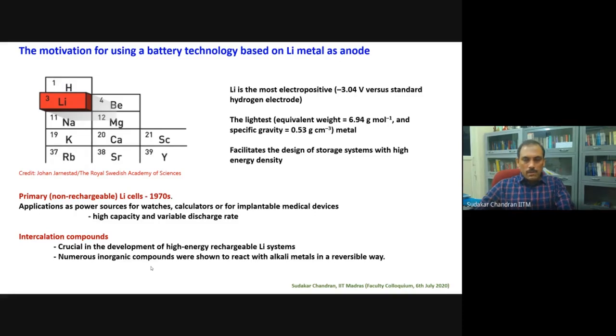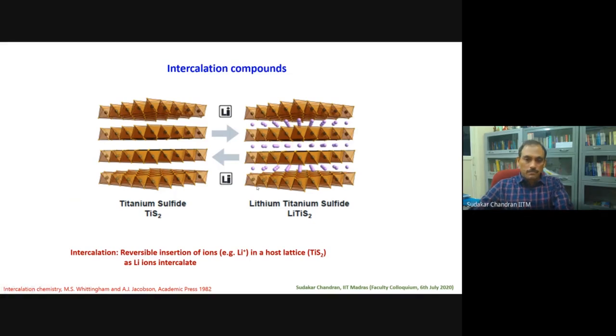Okay, so one other important thing which came up during the 1960s and 70s is the intercalation compound, for which Stanley Whittingham, in fact, coined the word. It was crucial for the development of high energy rechargeable lithium ion batteries. So many intercalation compounds came up during that time. For example, titanium disulfide is one example of an intercalation compound. In this compound, you can insert and remove the lithium ion without the structure undergoing any drastic changes. So these compounds are called intercalation compounds.